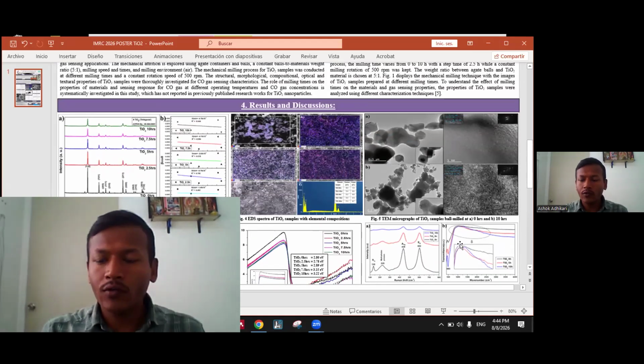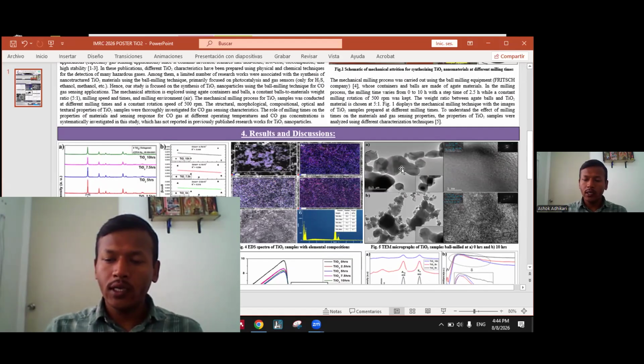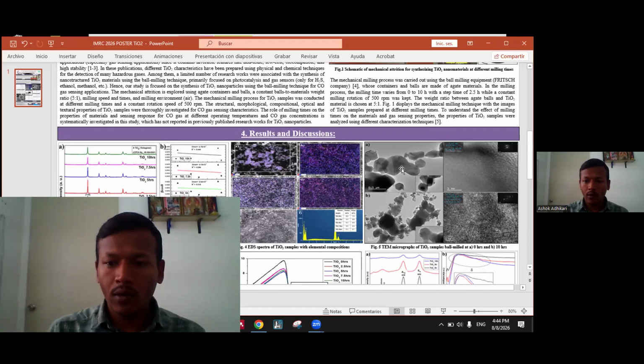So in figure 6 or figure 5, you can see further confirmation. We have checked the TEM results initially for the two samples, 0 hours and 10 hours. And at 10 hours we have also seen very small grains, which is compatible with the same results.